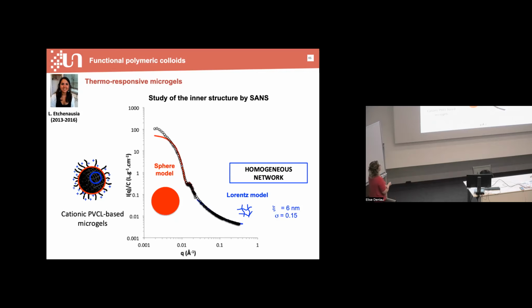What was interesting in this study is that we could characterize the structure of the microgel using SANS. In this case, we use two different models. One model at low scattering wave vector of a sphere, which is characteristic of the outer part of the microgel, and a Lorentzian model at a higher scattering wave vector, which gives a quantitative result of mesh size and polydispersity of the gel inside the gel, which are found very low compared to what is reported in the literature. So indicating that the microgels are really homogeneous networks.